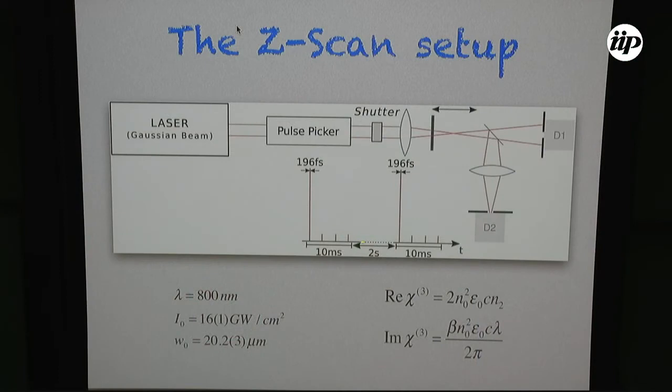So it's important to completely shut this laser, so that no laser is shining on the sample. After another peak of 200 femtoseconds, the amount of energy is very small. You will not change the temperature of your sample. So this is the important experimental setup, which will certainly give us a nonlinear electronic effect from your sample. You don't have the Soret effect contribution, neither the thermo-optical effect contribution, which usually is present in this type of experiment.